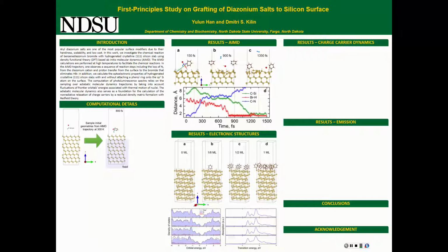So the main advantage and finding of this work is that one starts with a chemically intact precursor, and this precursor, while approaching the silicon surface, decomposes into fragments, and one fragment attaches to the surface, while another fragment departs to exhaust. And this is a healthy process as it creates a protected surface that is ready for optical and electronic applications.